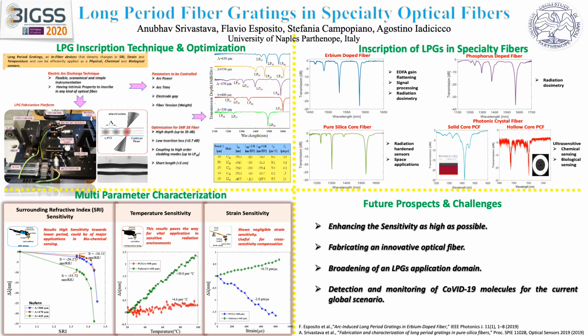For our work, we use the electrical arc discharge technique, which has gained much importance in recent years due to being flexible, economical, and having simple instrumentation, since it eliminates the need for expensive laser systems as well as removing the need for pre-hydrogenation of the fiber and consequent post-thermal annealing to stabilize the gratings. Actually, it creates the perturbation by applying an arc discharge to the fiber with a specific periodicity.